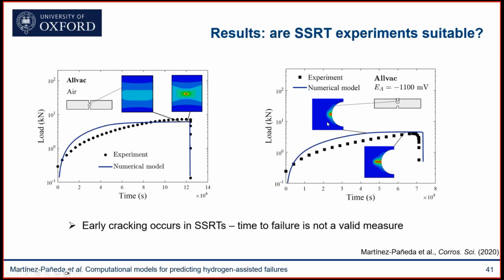And what we saw is that the model was also able to capture what you see in the experiment. So you get this kind of ductile instability in the experiments. But we saw that the model was predicting that cracking initiated relatively early in the experiment, and therefore made these SSRT experiments not suitable for assessing hydrogen embrittlement susceptibility. One has to do fracture experiments.